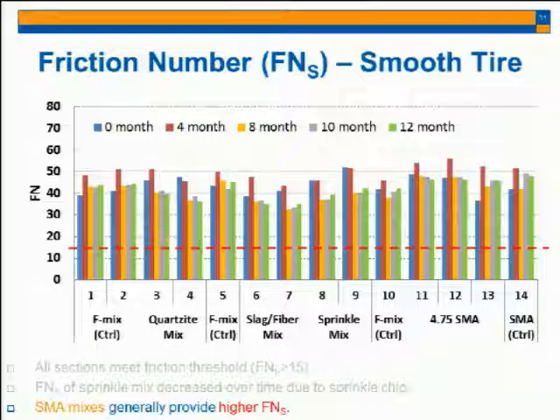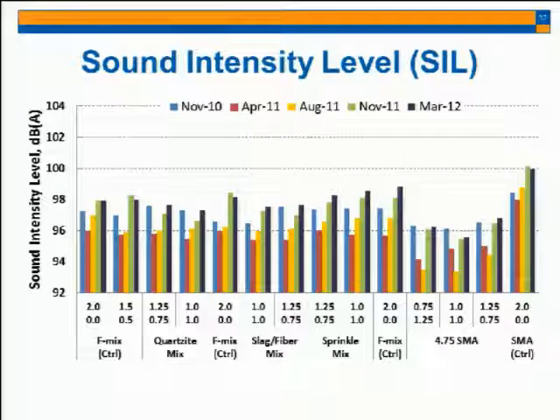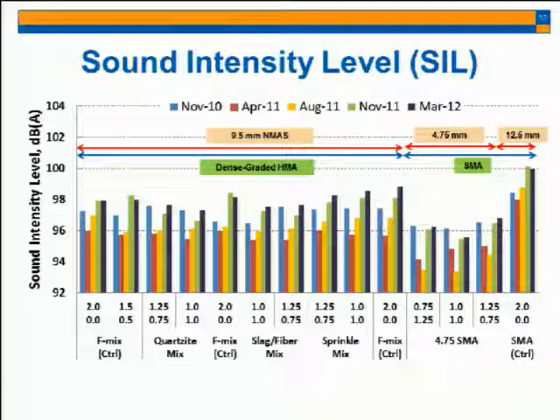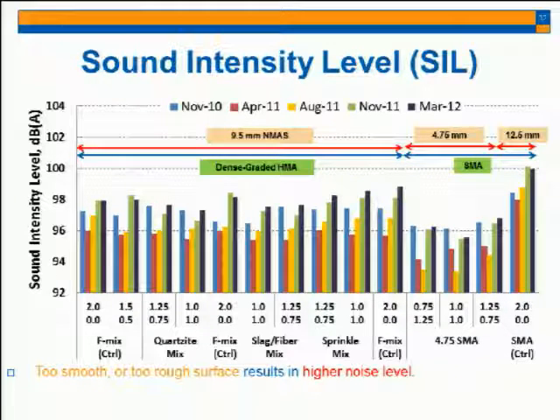So SMA mixtures generally provide a higher friction number. Sound intensity level: if the surface is too smooth or too rough, this causes a higher noise level. If we have the proper texture or surface voids, the noise is reflected in the voids and then diminished. But if it's too smooth, the noise goes into the air in the other area. If the surface is too rough, it creates some noise between the tire and pavement.